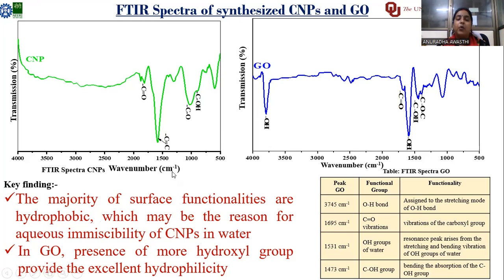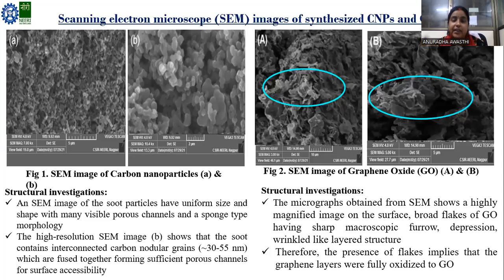So these features report the CNP, prepared by the method we used, as a hydrophobic CNP, and the other one, GO, as a hydrophilic material. For the application, we did scanning electron microscopy to understand the surface morphology. As you can see in the SEM image, the carbon nanoparticles are nodule, grain-type carbon material with a 30 to 55 nanometer size, and graphene oxide is a sheet-like material. Some macroscopic layers are found, and the flakes in this GO material were fully oxidized, and the material forms a hydrophilic graphene oxide.